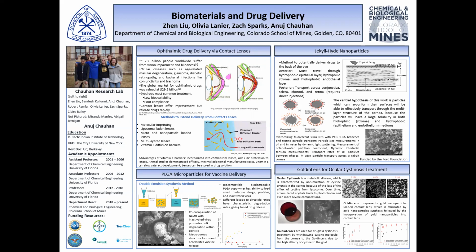The alternative with the microparticles is that they would be injected one time. As they sustain release over time, they would provide an immune response in the body that would be as effective or even more effective than the multiple injection approach. The PLGA polymer has advantageous properties, such as its degradation rates. It has a degradation regime that once it's first injected in the body would give an initial release, followed by a lag phase, and after further degradation, it would give a secondary burst release, which would match the same time in which the second booster shot would be given for the multiple injection approach.